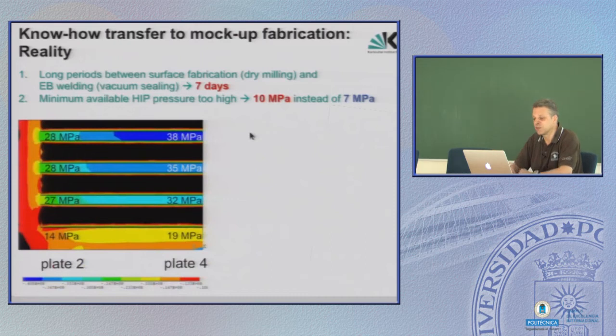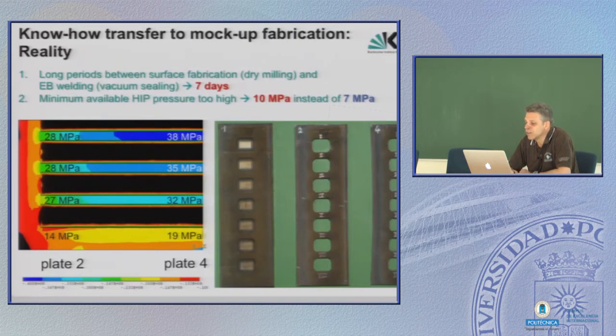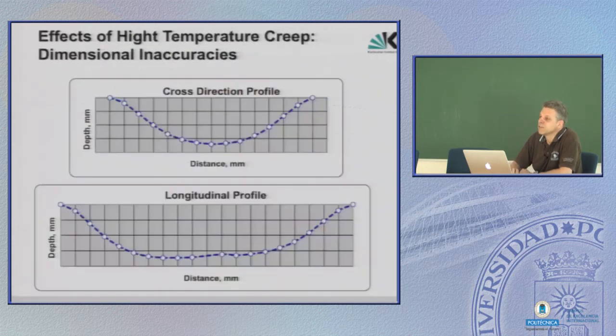So again, this was later on when we knew about this. And so the real stress distribution over the blade looks like that. In the end, in the middle of the blade, we had a maximum of almost 40 MPa pressure. And this resulted in what we expected. The blades, especially in the middle, have been deformed immensely. Here is the profile. This should be a straight line, but in both cross directions you have a severe deformation of the whole blade. And so what at the beginning looked rather promising, in the end resulted in such severely deformed blades which cannot be used for a first wall.